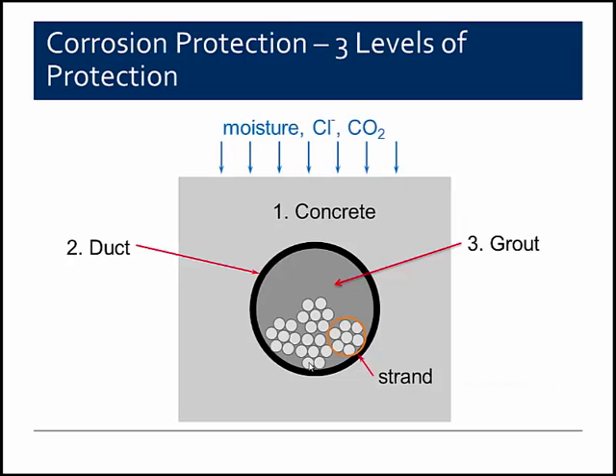The corrosion protection component of the grout: there are 3 levels of protection of a post-tension tendon, and the first one primarily is the concrete surrounding the tendon. In this diagram we've tried to illustrate these 3 levels. The second level of protection, or layer of protection if you will, would be the duct. Nowadays we use plastic ducts. In earlier years a corrugated metal duct was used, but the plastic has been shown to be more robust, have better leak control, and does a better job protecting the tendons.